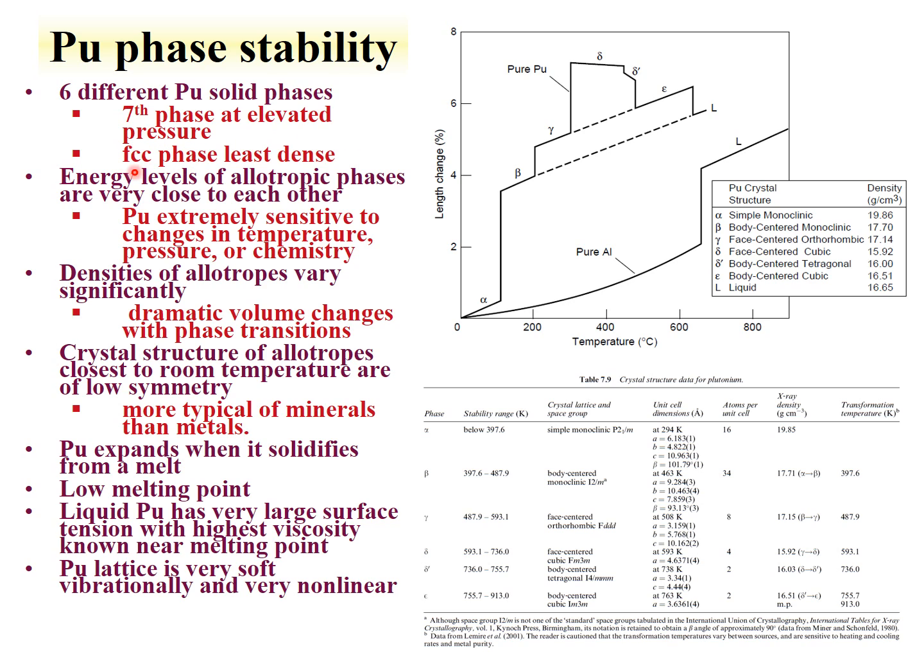The face-centered cubic is your least dense phase. All these phases are close to each other energetically, so that's why they can be reached through just heating the sample. The densities of these phases vary dramatically. The data is shown here, where the most dense phase is the alpha phase, which is close to 20 grams per milliliter, and the least dense phase is the delta phase, the face-centered cubic, or FCC phase, where you get a little under 16 grams per milliliter.